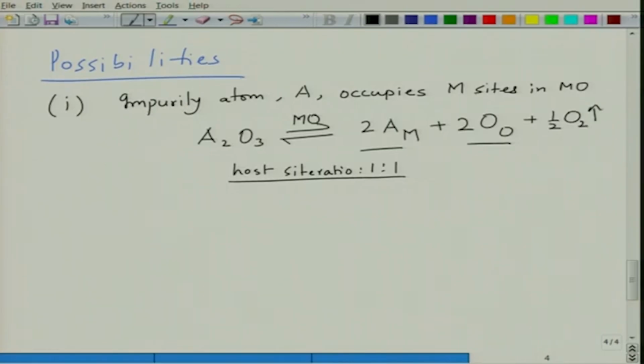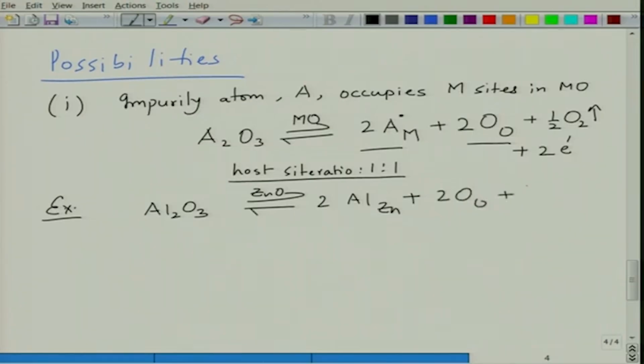go out. Now, this A is 3 plus, M is 2 plus, which means it will carry one positive charge. How is this going to be accommodated? By creation of an electron. So, this is going to give rise to 2 electrons. So, this is electronic compensation, which means impurity of A2O3 type will cause an N type behavior. So, just like example could be, if you have Al2O3 which let us say goes into ZnO, what will happen? This is 2 Al going to zinc site. So, this is example, plus 2 oxygen going to oxygen sites, and another oxygen goes out, and then 2 electrons.